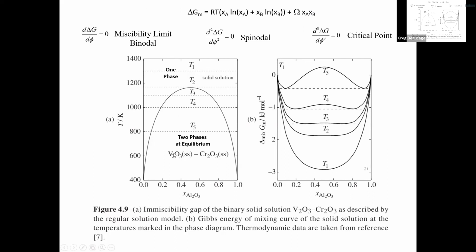This is a picture of mixing oxides and metals, and they form 2 crystal phases. One's a substitutional alloy, so that they totally mix above this temperature, and when you cool it down, they demix into these vanadium and chromium oxide crystals. Right. So if you plot that equation, because it's symmetric, in other words, XB is 1 minus XA, you can swap A and B and get the same answer. So it has to be centered on 50% here.